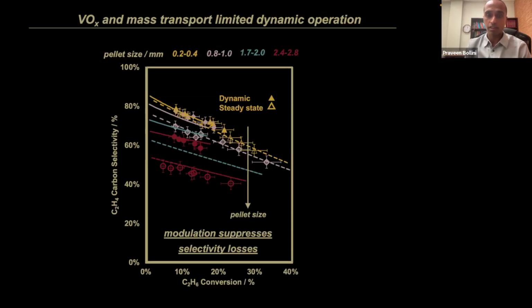So in the limit, let's say for 2.4 to 2.8 millimeters, which is the data shown in red, you have a significant difference between the dynamic selectivity and the steady state selectivity. The point that I'm trying to emphasize is there are phenomena that you can exploit, in fact, on industrial sized pellets that do not appear when you conduct experiments at particles that are hundreds of micron in size, which is what academics would typically do.